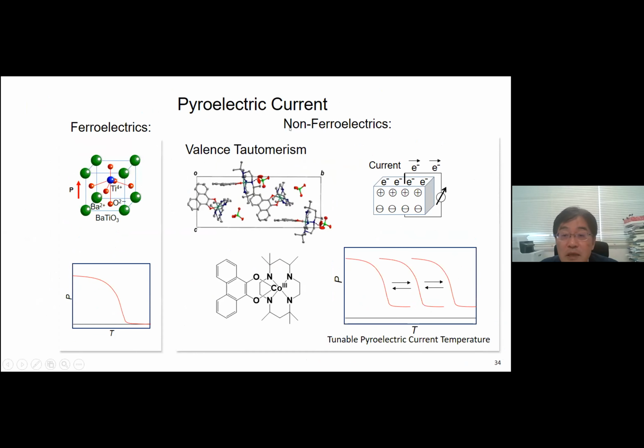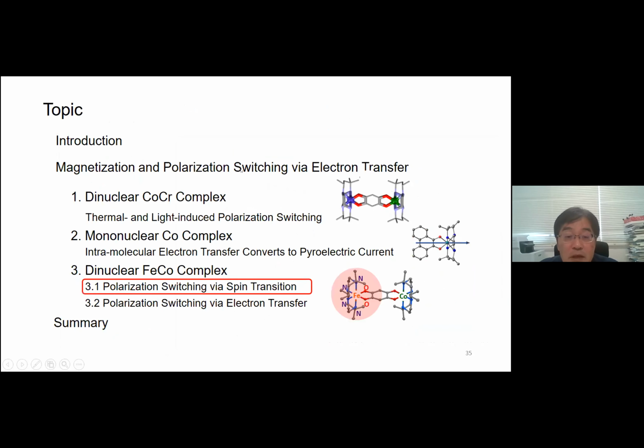So we reported pyroelectric current of this valence tautomeric compound with a polar structure. And usually it is difficult to control the transition temperature of a ferroelectric compound, but this is a valence tautomeric compound. So if we control the ligand redox potential, then we can control the transition temperature. This means the pyroelectric current temperature is controllable. This is an advantage over typical ferroelectric compounds. Okay, next I'm going to talk about polarization switching using spin transition.